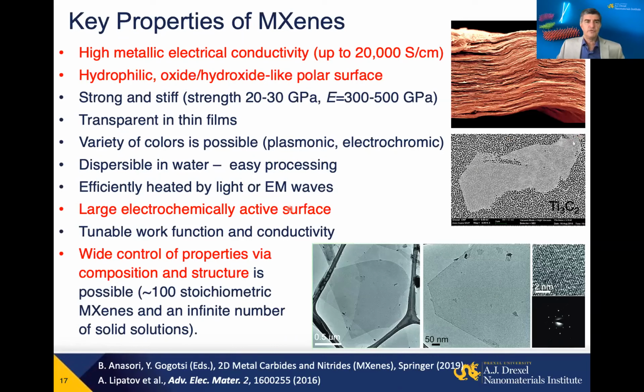Let me summarize what we have right now. We have this enormous family of materials with more than 30 stoichiometric structures and probably about 20 solid solutions and multi-element MXenes reported already. They are water soluble without any additives or binder, and can also be dissolved in polar organic solvents and processed, for example, into this type of multilayer film, or you can use single flakes. You can see they look like many other two-dimensional materials. If you look at this transmission micrograph, they're single crystals, as electron diffraction and high resolution TEM show.